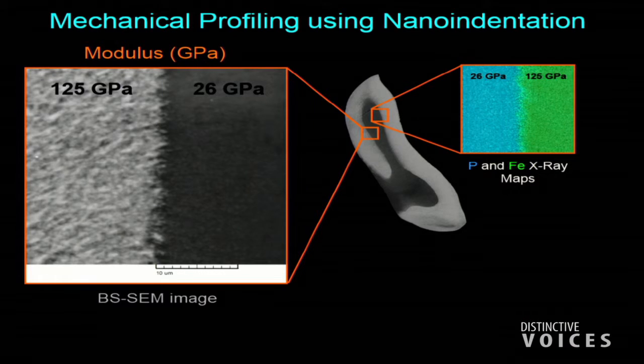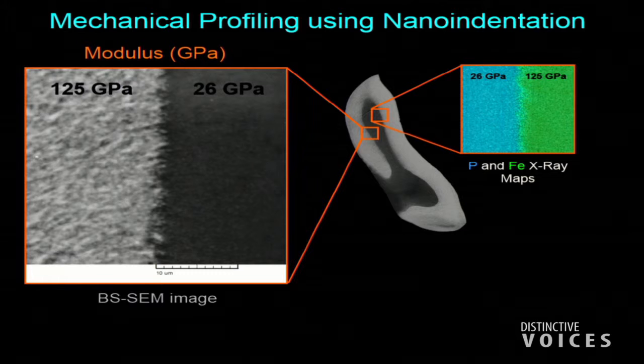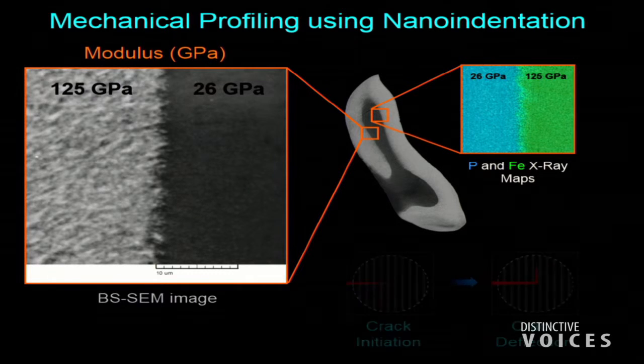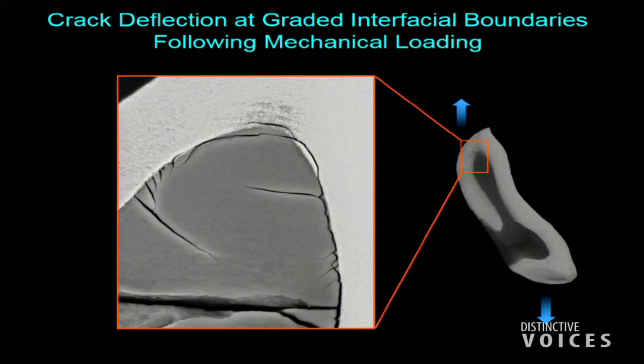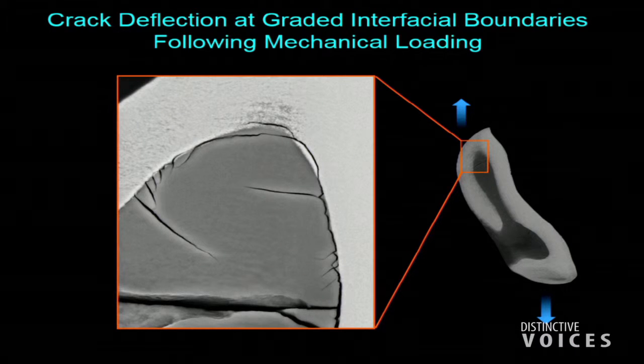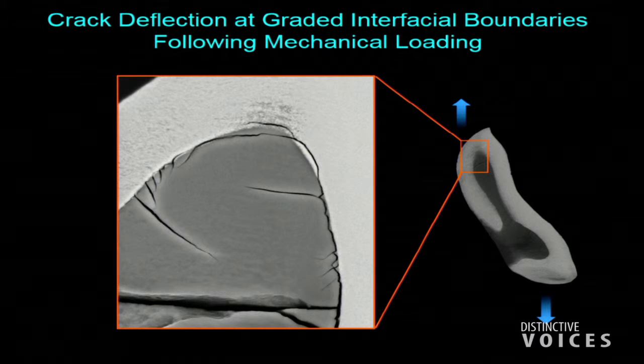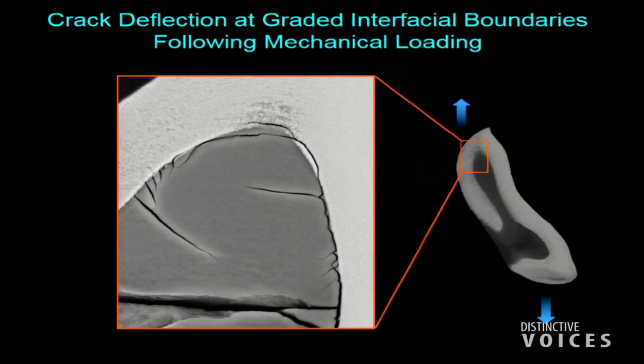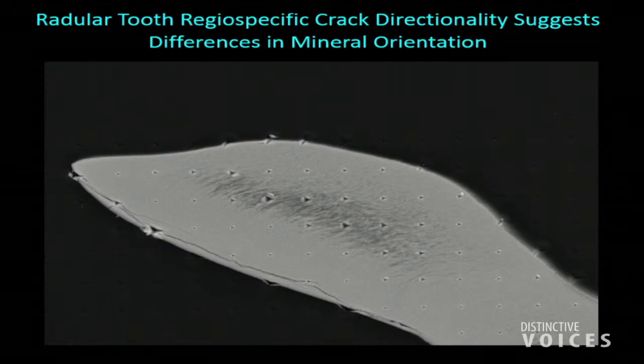And so if we look at these teeth, here's the core of the tooth, here's the shell of the tooth, here's the stiffness. If I do my basic math, it is greater than a factor of 4. We would expect cracks to be deflected, right? And so here we see a crack that's in the core of the tooth. It propagates, but it's deflected by the shell. So this just shows this interface. This is one way that biology uses its structures to toughen its components.